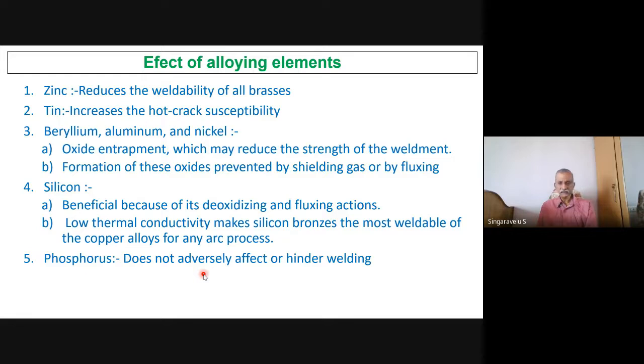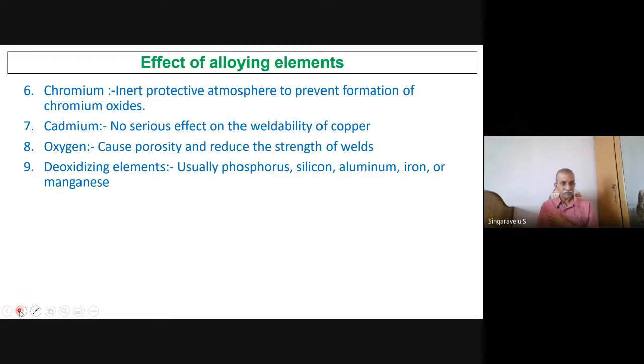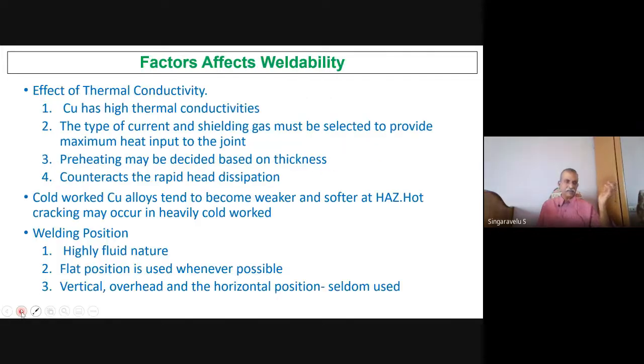Phosphorus does not affect, right? Chromium needs an inert protective atmosphere to prevent formation of chromium oxide. Cadmium, no serious effect. Oxygen causes porosity and reduces strength. Some deoxidizing elements, usually phosphorus, silicon, aluminium, iron, have been added. Right? This is with respect to the effect of alloying elements. Coming to the weldability part, what are the factors which are getting affected? Effects of thermal conductivity. Copper has a high thermal conductivity, right? The type of current and shielding gas must be selected to provide maximum heat input because heat is immediately dissipated. Preheating is decided based upon the base material thickness.